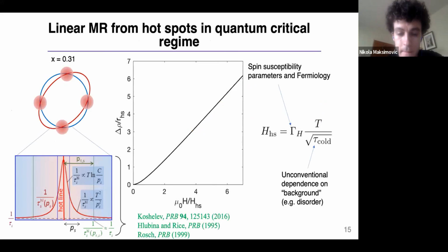The thing about the magnetoresistance is it's true that you will get contributions from each band individually. The regions that dominate the magnetoresistance are actually these quasi-particle sinks. So in our work, we've completely neglected the magnetoresistance arising from these cold regions.